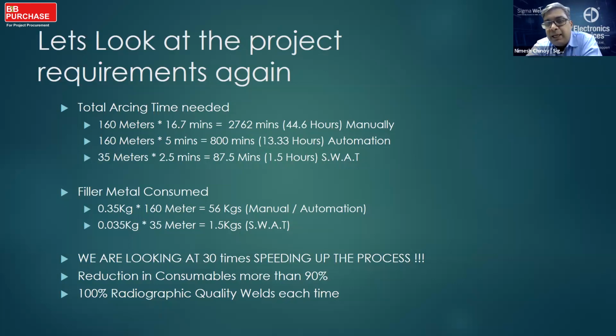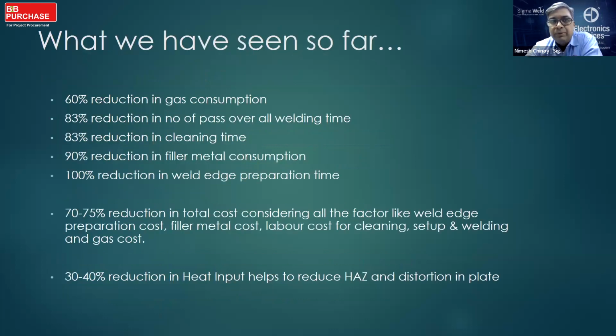You're looking at speeding up the process 30 times, reduction in consumable more than 90%, and 100% radiographic welds each time. So far we have seen that you can have 60% reduction in gas consumption, 83% reduction in number of passes and cleaning time, 90% reduction in the filler wire consumption, 100% reduction in the weld edge preparation time, and overall 70 to 75% reduction in the total cost, considering factors like weld edge preparation, filler metal, labor costs, cleaning, setup, welding, and gas costs.